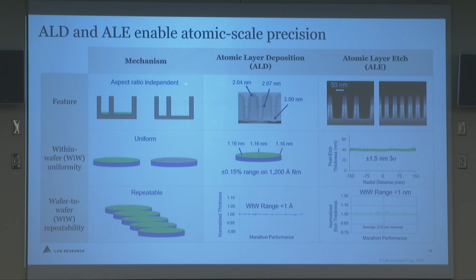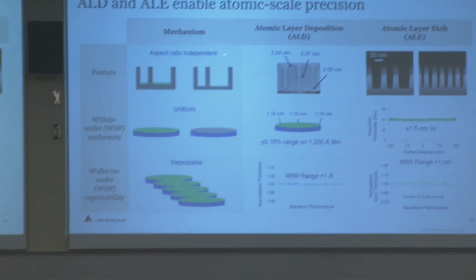It can give us really good uniformity across an entire 12-inch wafer and really good repeatability, the same from wafer to wafer. So these are real examples, like for the deposition, looking at that very middle graph there. That was a thicker film example, but looking across an entire film that's 1,200 angstroms thick, the variation was less than 0.15%. And the repeatability from wafer to wafer was less than 1 angstrom variation. So, that's the kind of precision that's required for high volume manufacturing and that we gain from these new techniques that we've developed and brought to market.